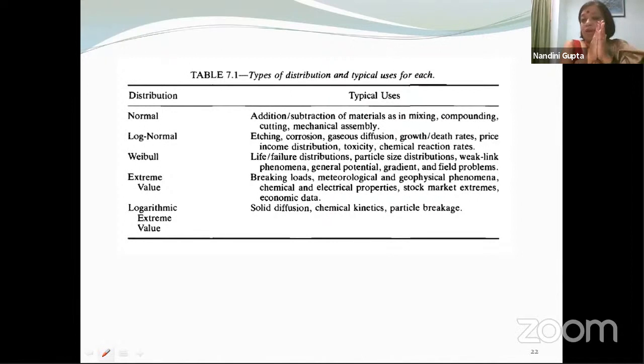Because, for example, when you're talking about breakdown, it does not matter what is the average property, the variation of the property. We are not interested in the average property. We are interested in that one property, which is the weakest link. So if this material has one weak link at one particular position, even if elsewhere, on an average, the material is very good, the weak link is what we are interested in. So whenever we are looking at weak link phenomena or extreme value statistics, it is the Weibull distribution that best describes the distribution that we would have.